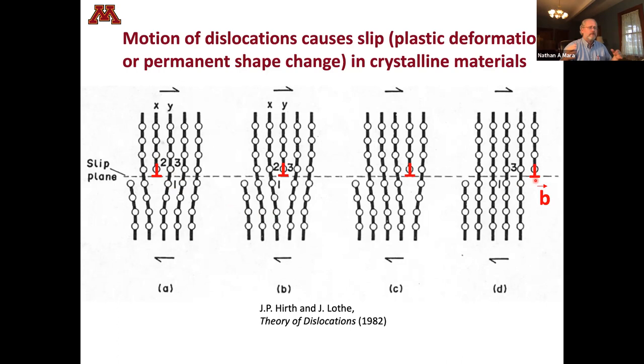You can put a radius onto something. You can stamp a part out. This is what enables this. So how dislocations interact with each other and how they interact with interfaces is key to how the mechanical response of the material ensues. And so we actually denote this with this Burgers vector, B, which has both a direction and a magnitude. And in this case, it's this magnitude between atomic planes here.